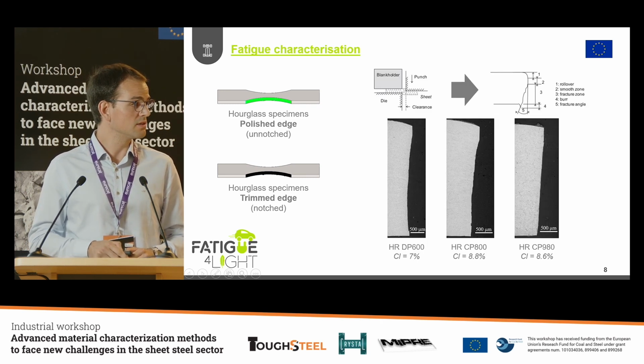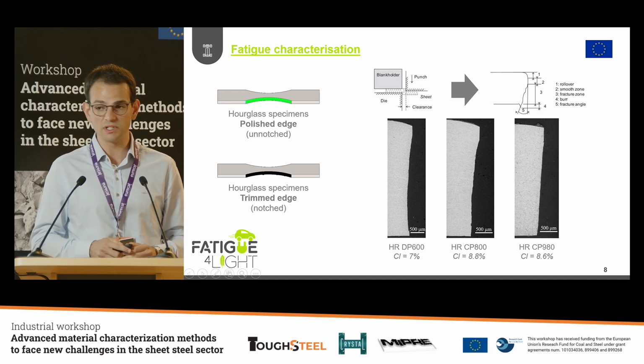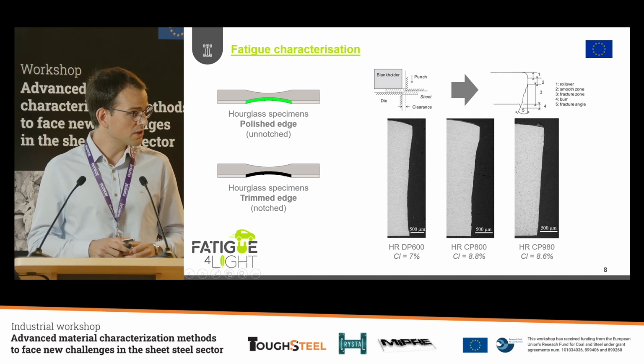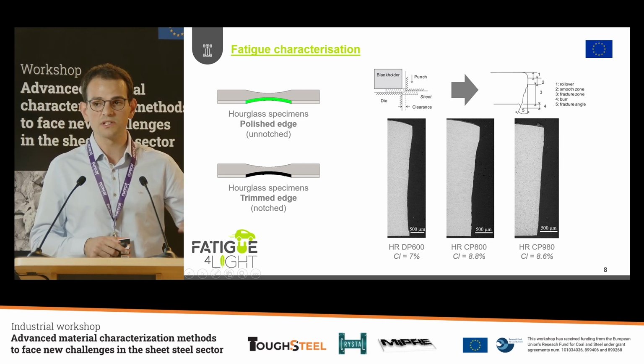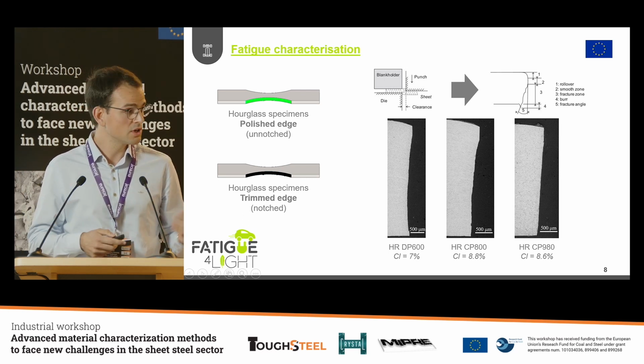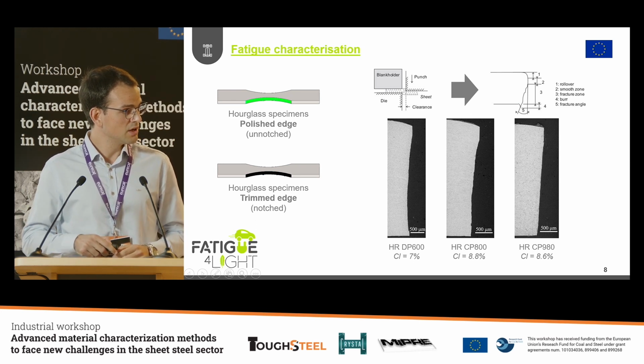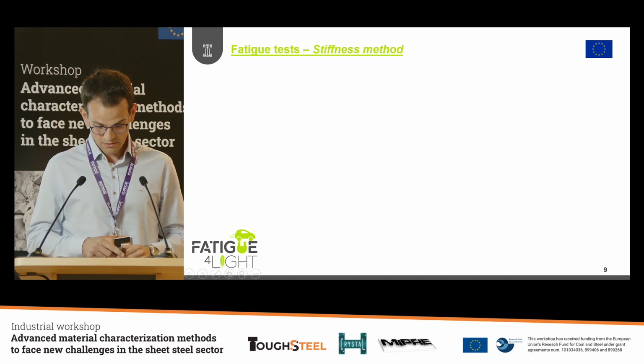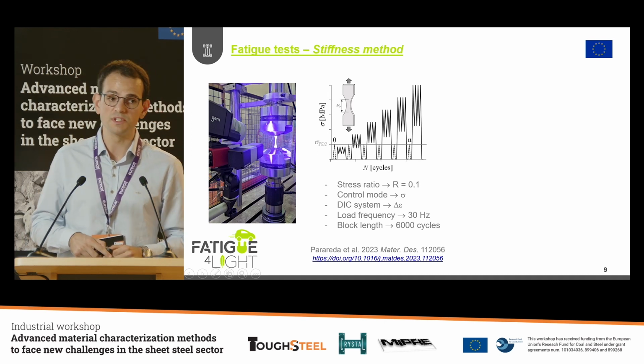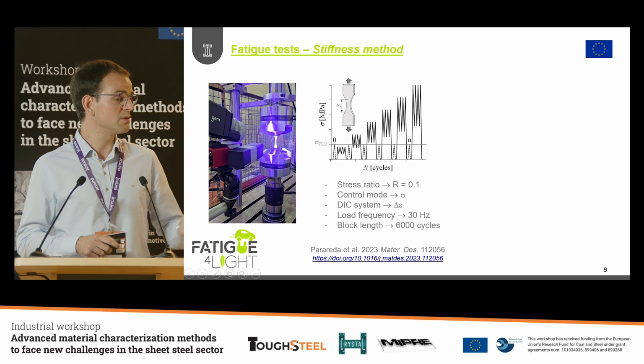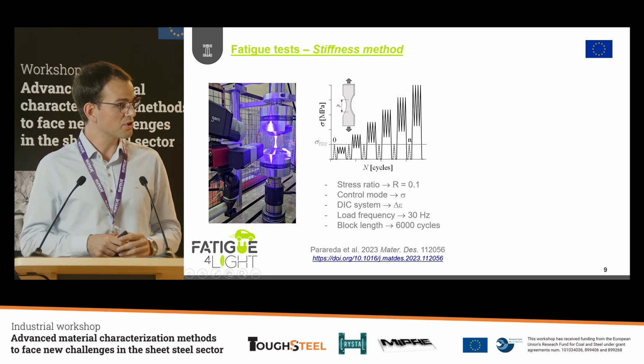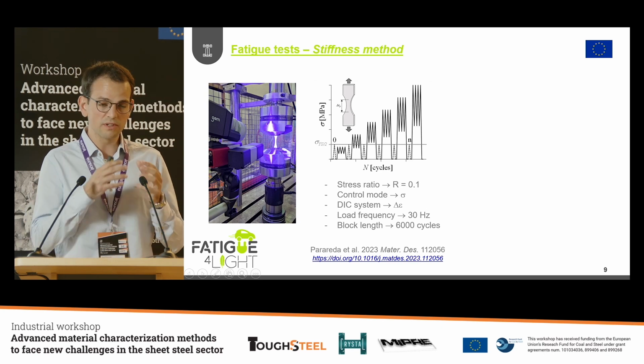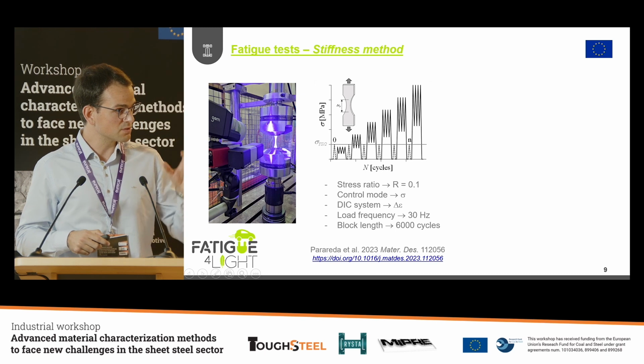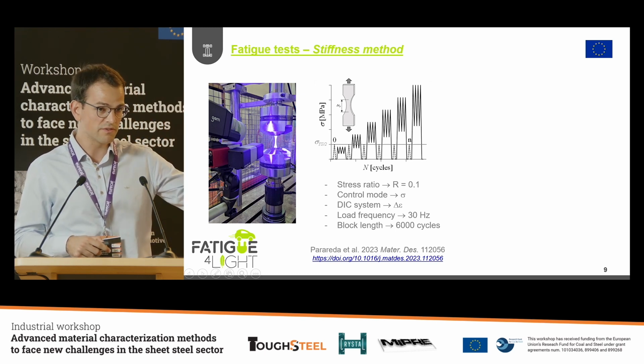The trimmed specimens were obtained by simply shearing the material, and we obtained the well-known sheared edge morphology, where we have this plastic deformation, but also these small defects that we are introducing due to the fracture of the material in these operations. In this case, we trimmed the materials with the same or almost the same clearance, and we tested the fatigue behavior of these materials. In this case, we used a rapid fatigue method that we developed in the Fatigue4Light project. This method is based on seeing how the fatigue damage is evolving during this fatigue test, where we are increasing the stress amplitude between these different fatigue blocks.